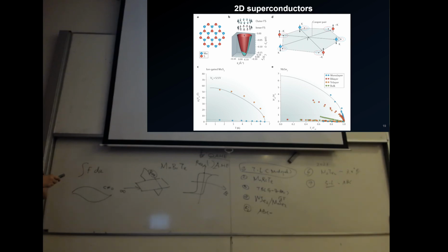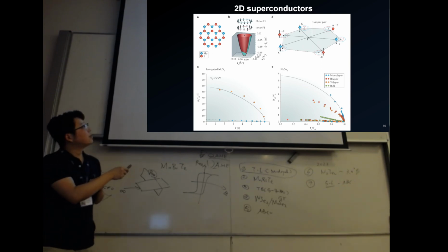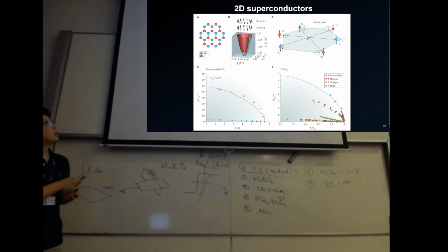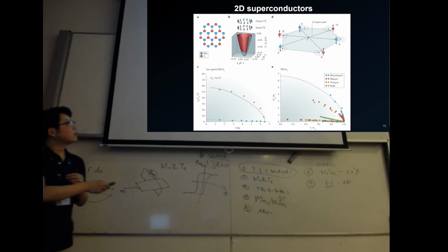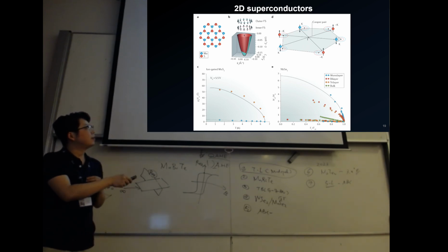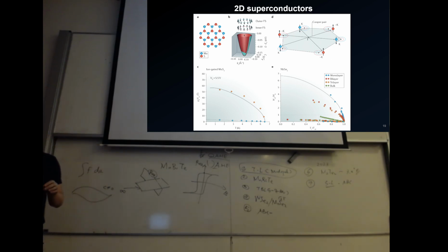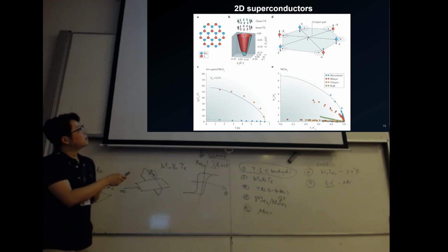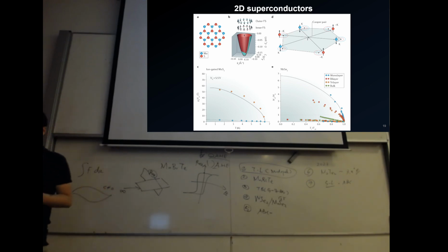So these are two examples: MoS2, gated by ionic gate, and also another example of niobium diselenide. There is no ion gate, it's just a solid gate. Both of them show that if you have a perpendicular magnetic field, the superconductivity will be killed very rapidly. But if you apply your external magnetic field parallel to the plane, it's so robust that it's a lot of times higher than the Pauli limit. You know, the Pauli limit in BCS theory is defined by 1.8 something times Tc, right?